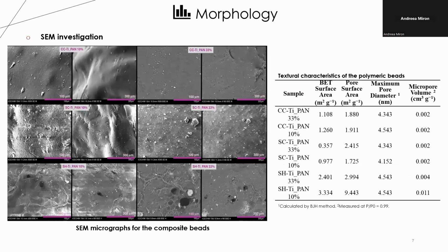All the beads present little variation in pore diameter and volume, which means that the filler has a very low influence on the porosity of the composite beads, regardless of the amount used. The largest bead surface area was recorded for the sample SH-Ti PAN 10%, which also revealed the largest pore surface area and micropore volume. The obtained data from BET analysis were also confirmed by the morphology by the SEM investigation, which